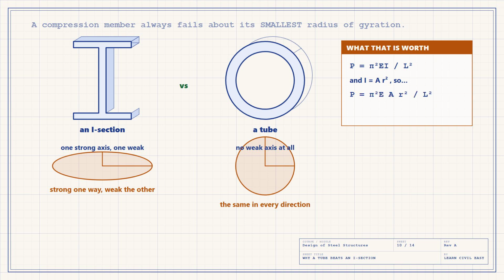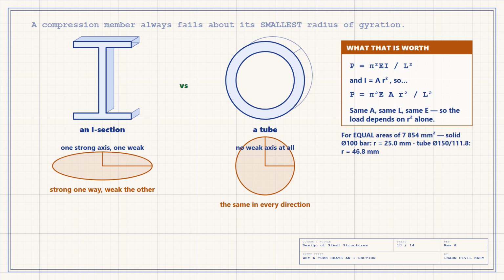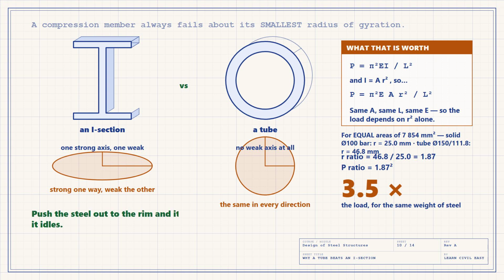Now the Euler buckling load is pi squared EI over L squared, and I is A r squared, same area, same length, same steel, so the load depends on r squared and nothing else. 46.8 over 25 is 1.87, square it, 3.5. The tube carries about 3.5 times the load. For exactly the same weight of steel, push the material out to the rim and it works. Bunch it at the center and it idles. That is the entire argument for tubular struts and tubular trusses. Against it, the connections are harder. The inside cannot be painted, so the ends must be sealed, and it costs more per ton.